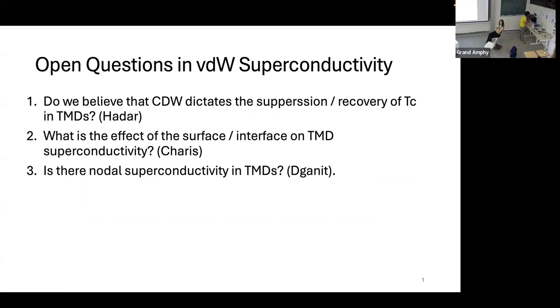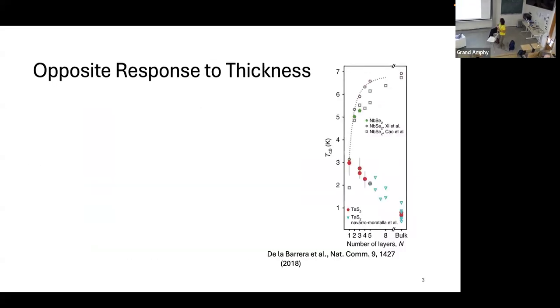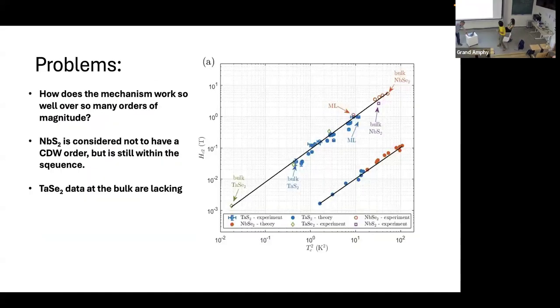So when I was showing this data on the universality, this data set here, I presented the theory that the culprit for this tunability is a charge density wave. If you look at a superconductor that is tuned in such a way, you have to ask what can be tuned. One parameter that can be tuned is the coupling lambda. But why should lambda be tuned in this particular way?